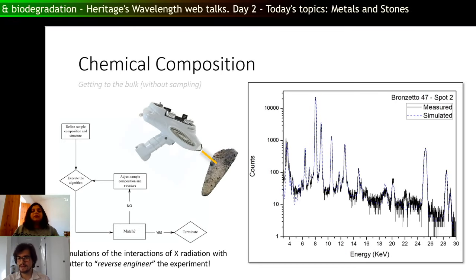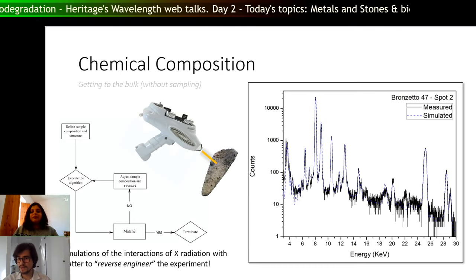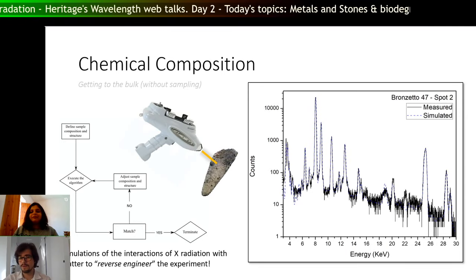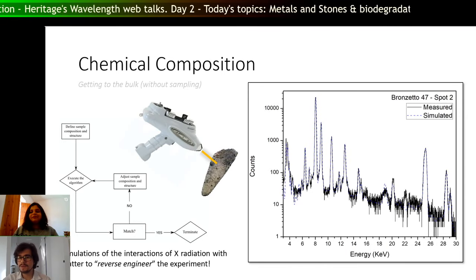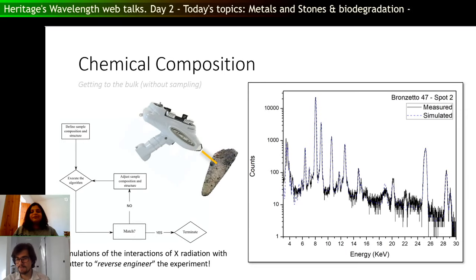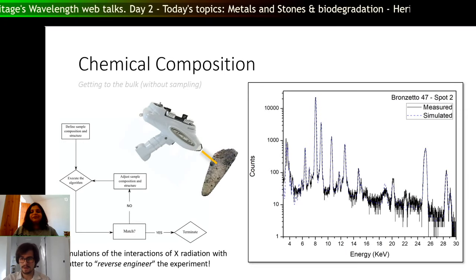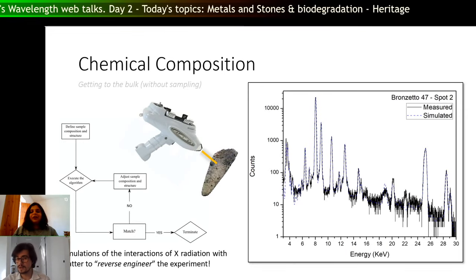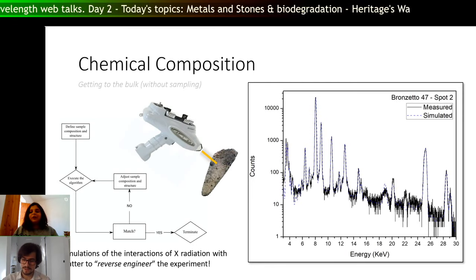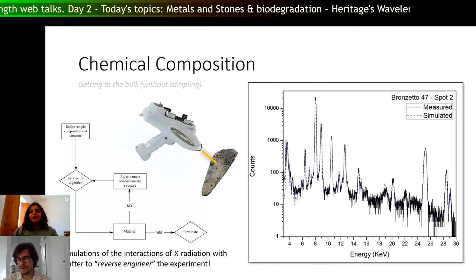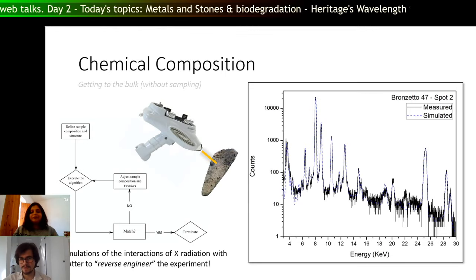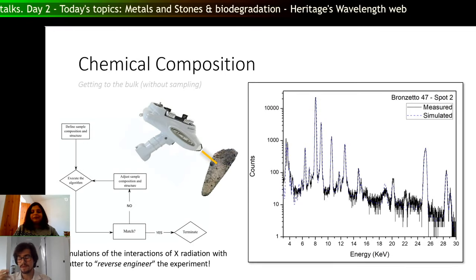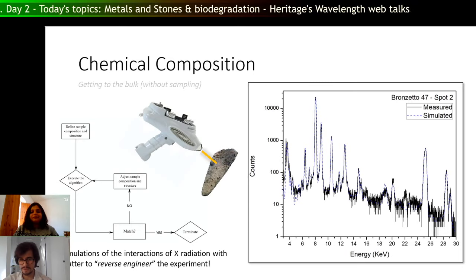You will compare that XRF spectrum simulated by the computer with the real one. And then you will see the differences. So you have a higher peak here and there, a lower one here and there, a higher contribution in this region or in the other, and you change your parameters. This requires quite some experience with X-ray fluorescence to adjust these simulation parameters. So that's why it's a very time-consuming process.